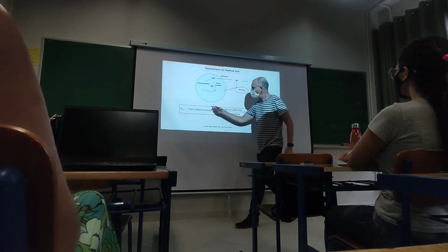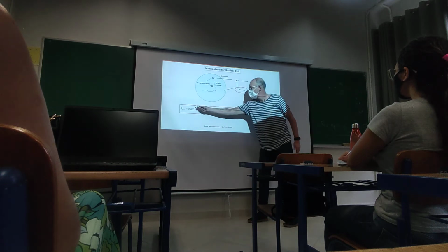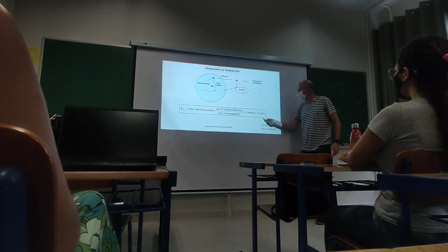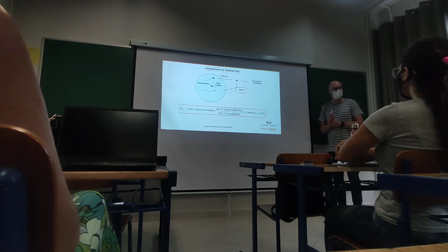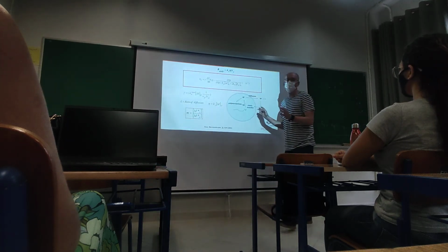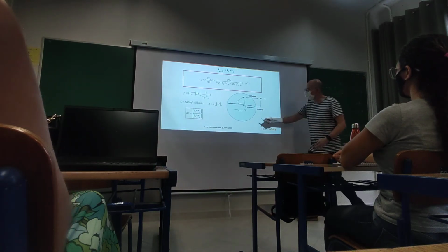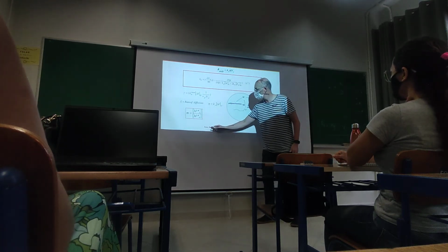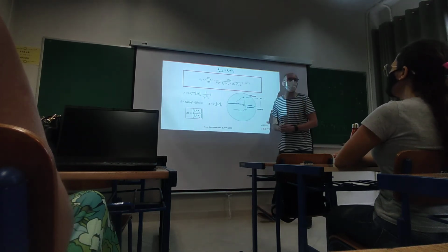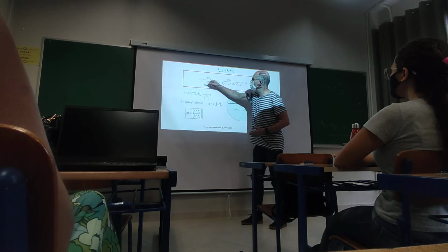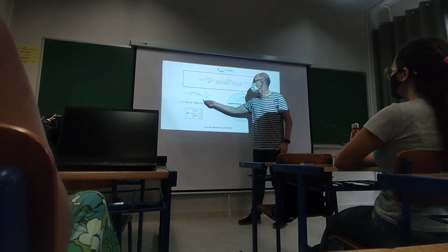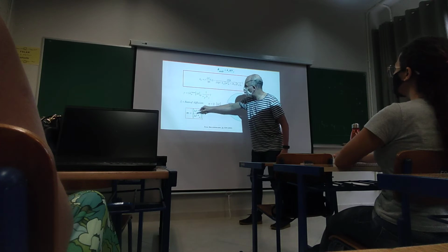Okay? These terms are normally expressed by a desorption or exit coefficient multiplied by the average number of radicals multiplied by the number of particles. The kd, like before for the ka, can be calculated. I will not go through it. You have here a reference where you can follow the description of how the desorption coefficient is calculated. But the desorption coefficient depends on this gamma, which is the rate of transfer to monomer, and depends on the propagation and on the partitioning.